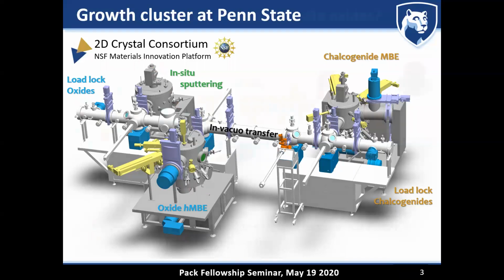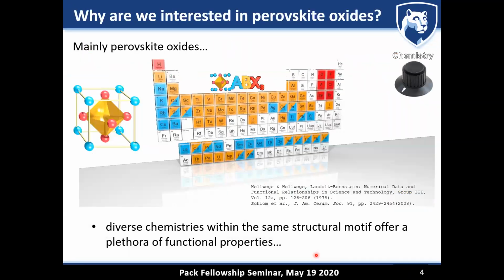And we are predominantly focusing on perovskite oxides. The perovskite structure is shown here on the left. We are quite intrigued by the perovskite structure because we can fit a diverse set of chemistry into this very same structural motif. Just to give you an idea of what you can put on the A side and the B side, the A side being shown here as blue and the B side being in the body center of this conventional unit cell, you can see that pretty much the entire periodic table can be put into this crystal structure.